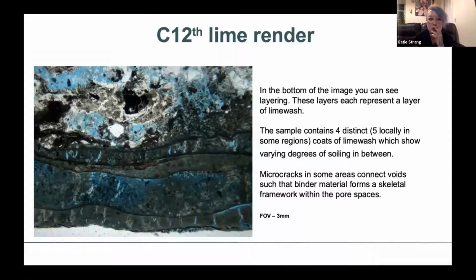And the reason that lime wash is so good, and why modern paints aren't as good, is that lime wash allows your material to breathe, whereas with modern film-forming paints, you see it on buildings quite a lot, especially externally where stonework has been painted, you end up getting big bits of paint flaking off. It was similar to what was happening here, but instead this was actually just lime wash.